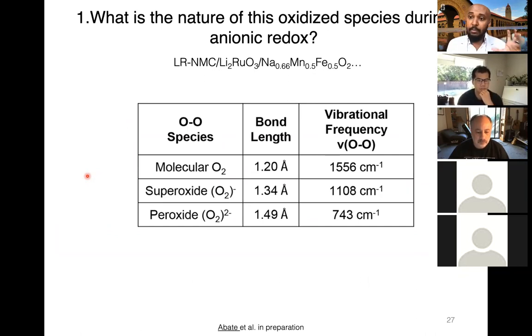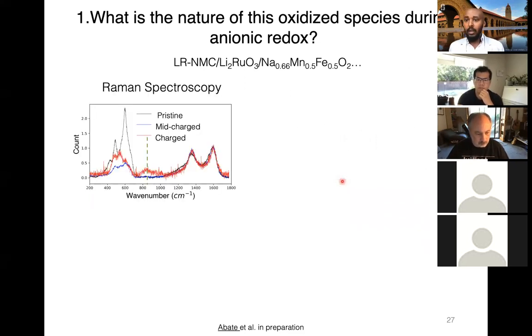So the previous slide was based on the electronic structure, but here you can see that the different oxide species also have different bond lengths and different bond vibrations. So one can use Raman spectroscopy to measure this bond vibration. And a typical Raman spectroscopy for cathode material is shown over here, where I'm showing the Raman spectra of the pristine material shown in black.